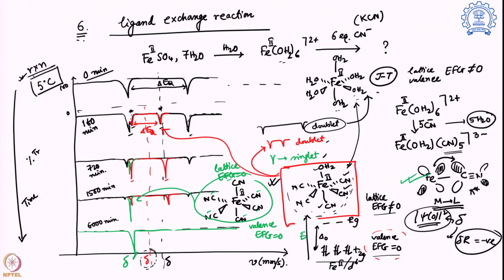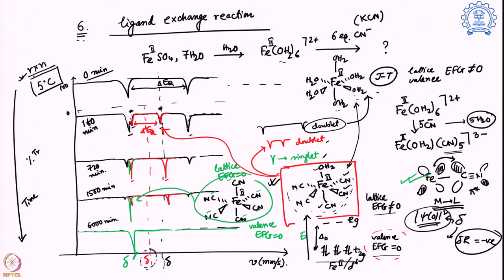Furthermore, pi electron movement from the metal d to the pi side of the orbital is actually triggering further electron density out of the metal system, which is bringing down the d electron density, increasing the propensity of s electron density to be present in the nucleus, which is multiplied with the negative term of delta R, and I am moving toward the negative side. So that is what is actually happening over there in the system.